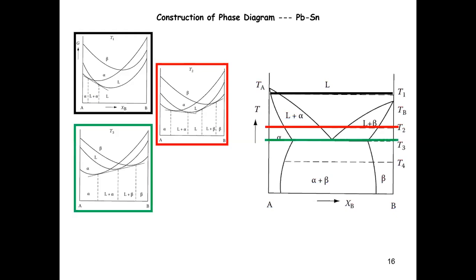Now, here is the more interesting scenario. If you keep on lowering the temperature, you're eventually going to achieve a very delicate temperature such that all three curves are aligned in a way that you can construct not a double tangent for two phases, but a triple tangent, right? Which is common to all three phases. Does this make sense, or is this understandable to everyone? I just want to make sure.